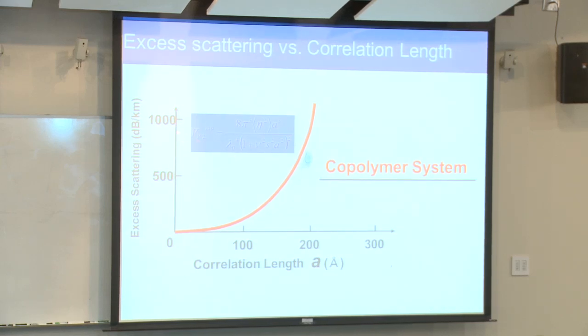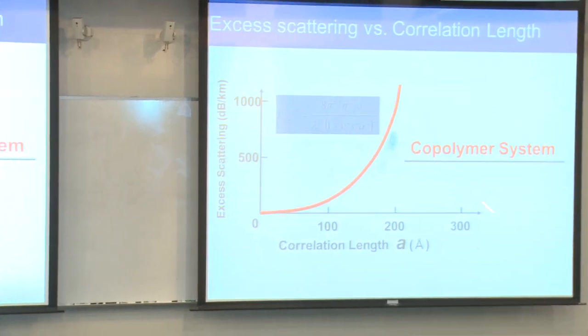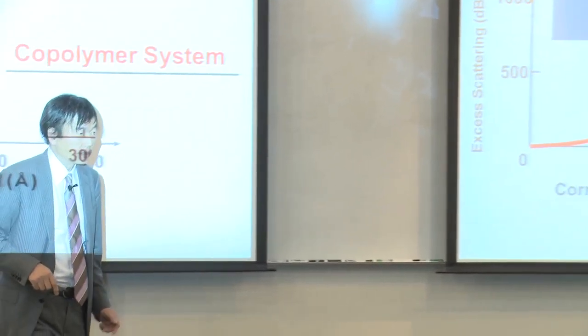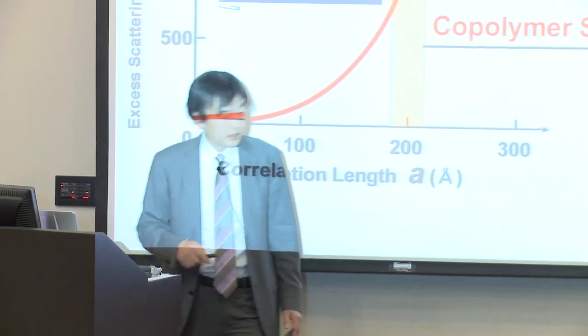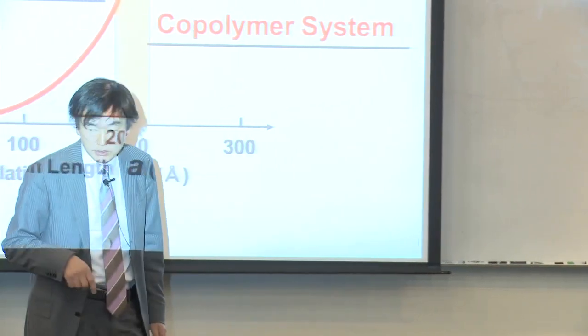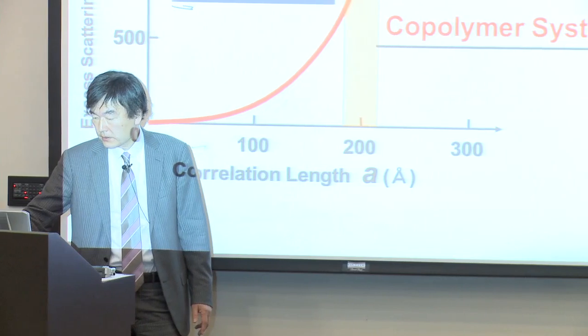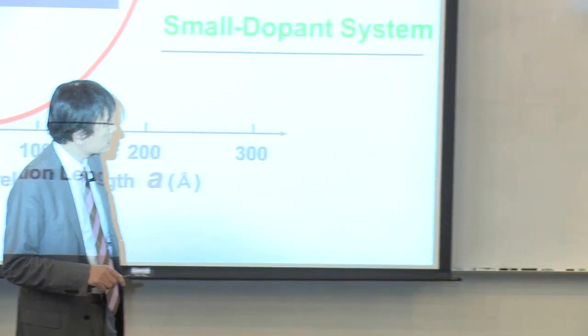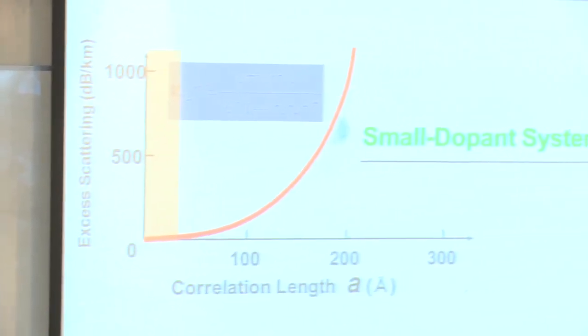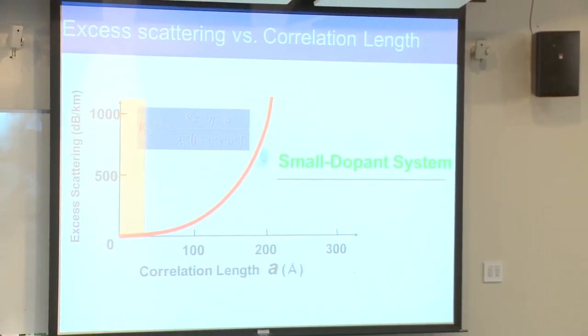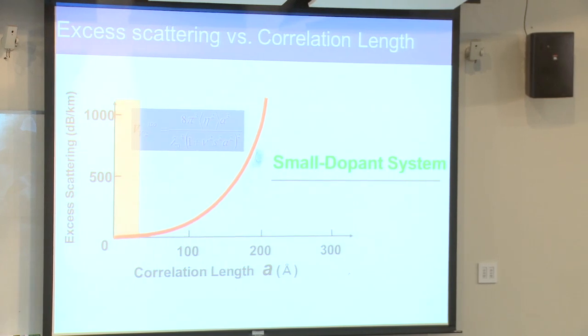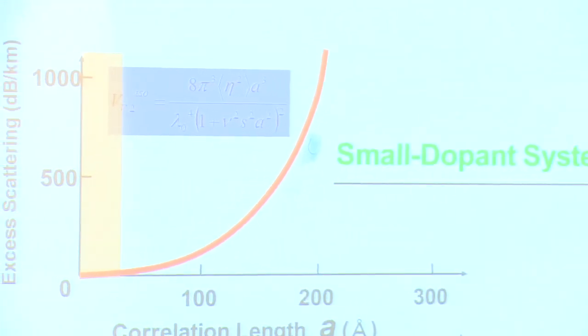Okay, now, this is the schematic representation of this equation. The scattering loss is the ordinate, and the abscissa is the correlation length. It corresponds to the size of the heterogeneities. In the case of the copolymer, it might be 200 angstroms or more. Then that's almost 1,000 dB per kilometer. Adding the small dopants, the size of the small dopants is around here. So we can almost completely eliminate excess scattering loss by adding a small dopant. And the small dopant has a concentration distribution in the radial direction. That is the idea.